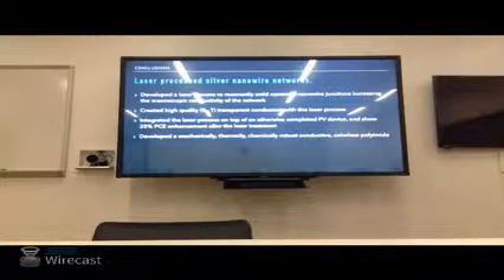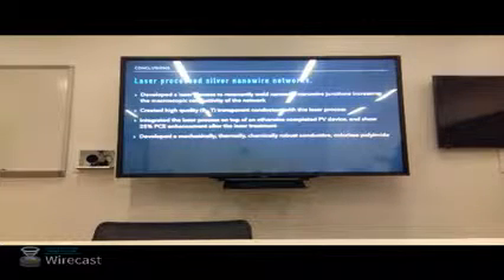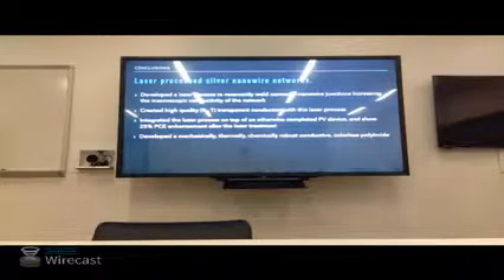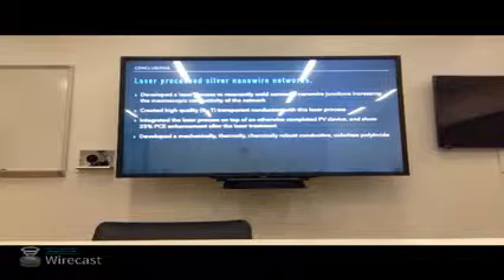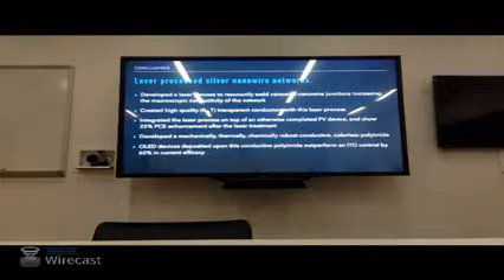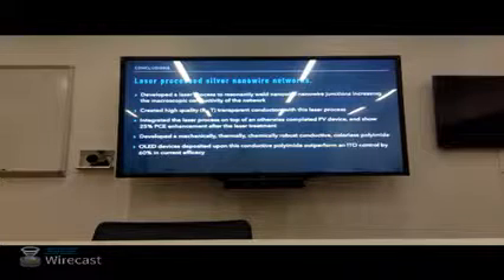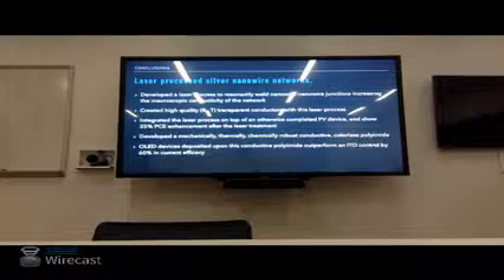Moving on, we developed a mechanically, thermally, chemically robust substrate and electrode for vapor-deposited organic electronics. And we showed the example of an OLED device built upon this composite material, which can outperform an ITO control by 60% in terms of current efficacy.